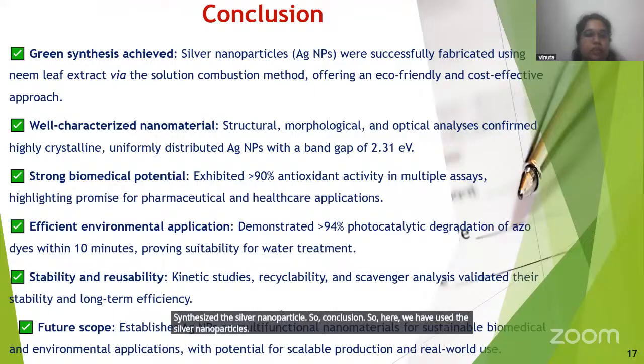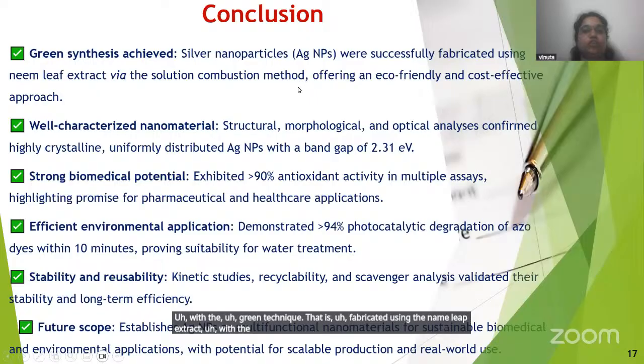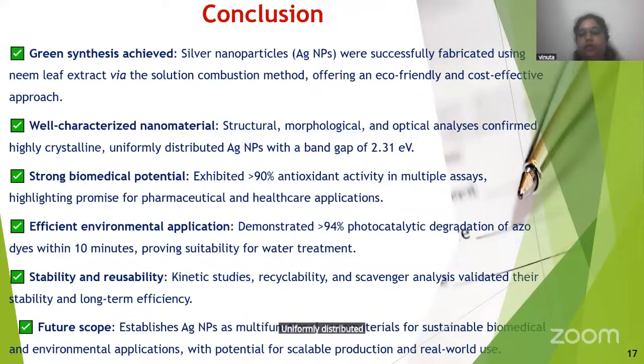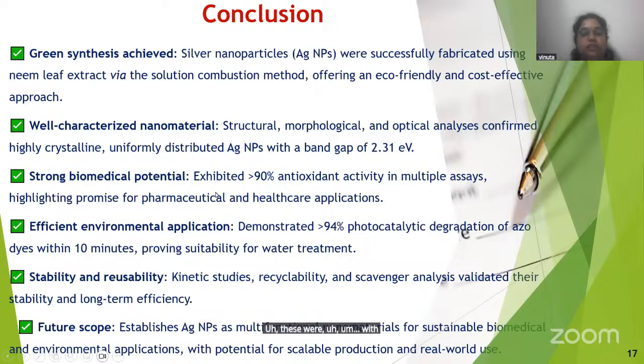So here we have used silver nanoparticles with the green technique, fabricated using neem leaf extract with the help of a solution combustion method, offering an eco-friendly and cost-effective approach. These were characterized, and their structural, morphological, and optical analysis confirmed highly crystalline, uniformly distributed silver nanoparticles with a band gap of 2.31 eV. These were tested with various antioxidant assays. This shows 90% antioxidant activity in multiple assays, highlighting the promise for pharmaceutical and healthcare applications.